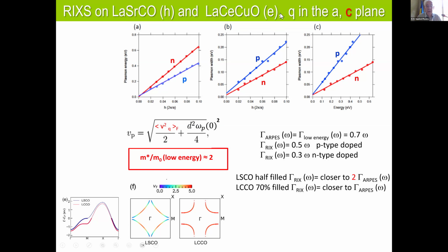And then when you go here to the width as a function of energy, we see a width which can be explained by twice the single particle self-energy. But for the n-type doped system, we see a reduced increase of the width as a function of energy. And this may again be related to the filling of the band structure, because if you have more and more filled band, then the transition into unoccupied states is reduced, and therefore the scattering rate is reduced as a function of momentum.